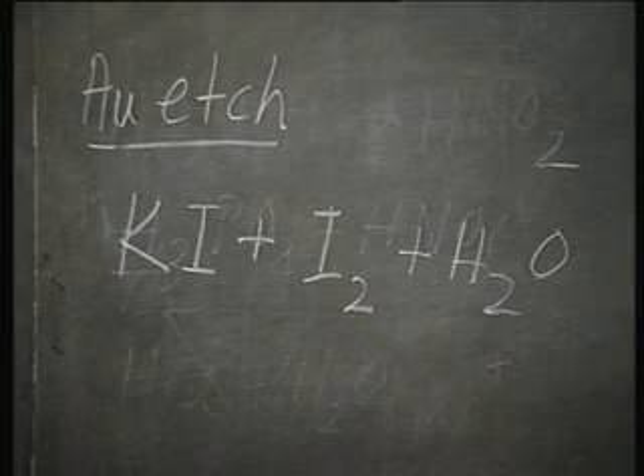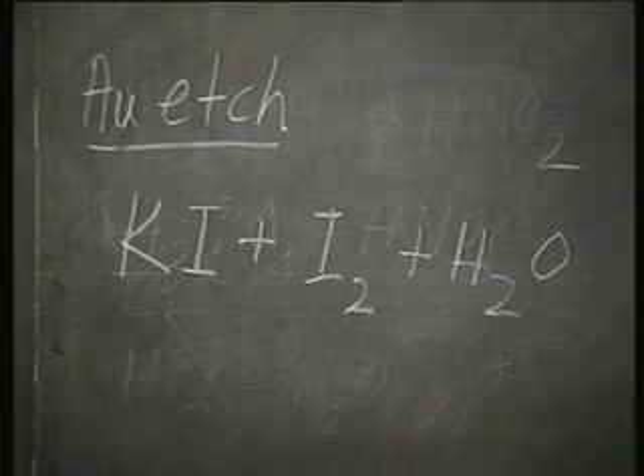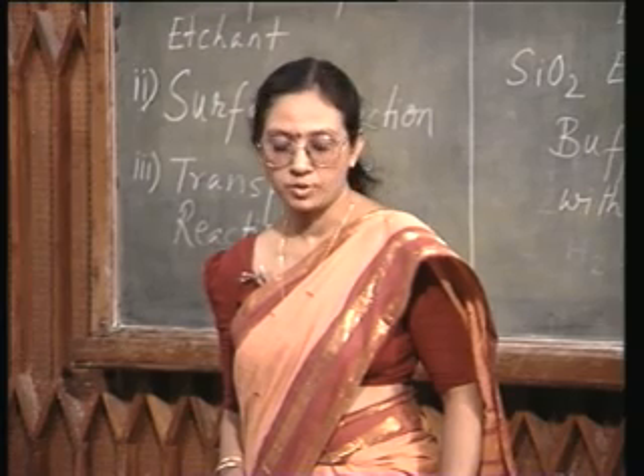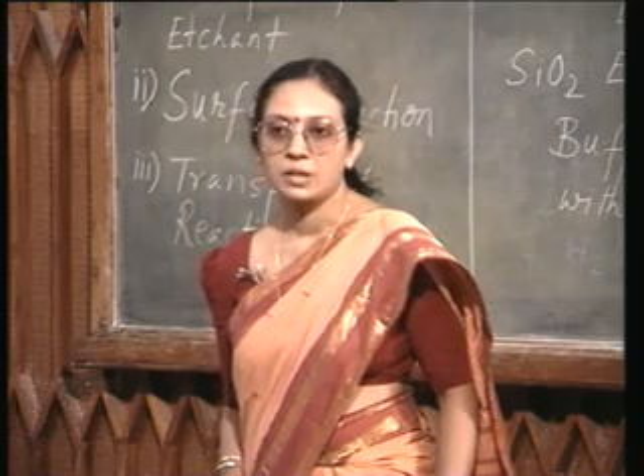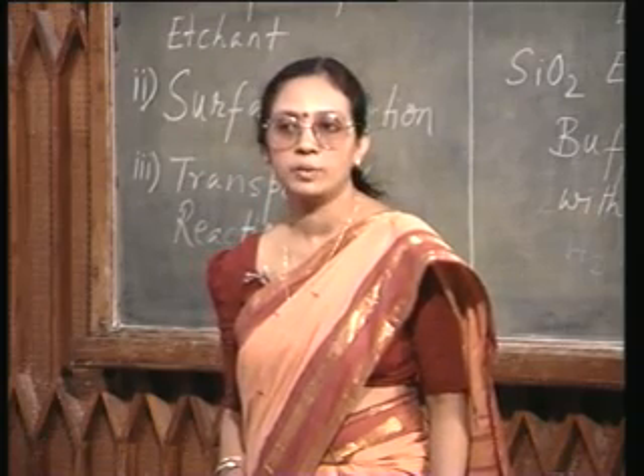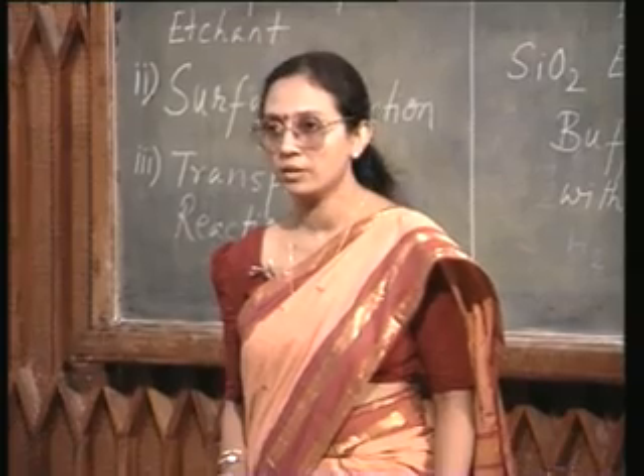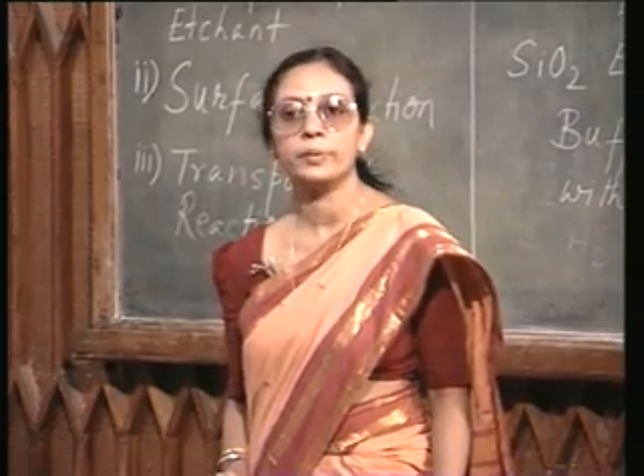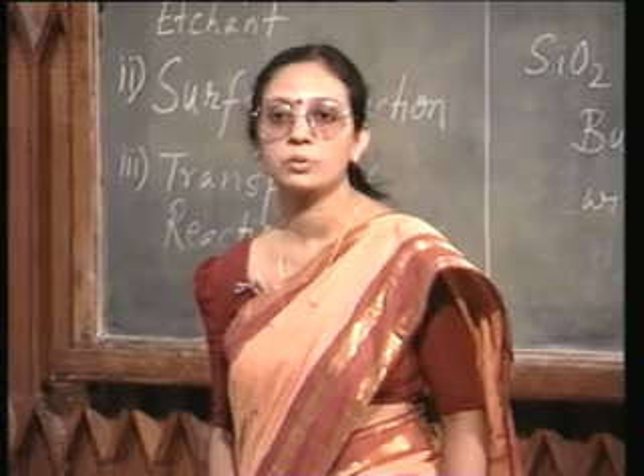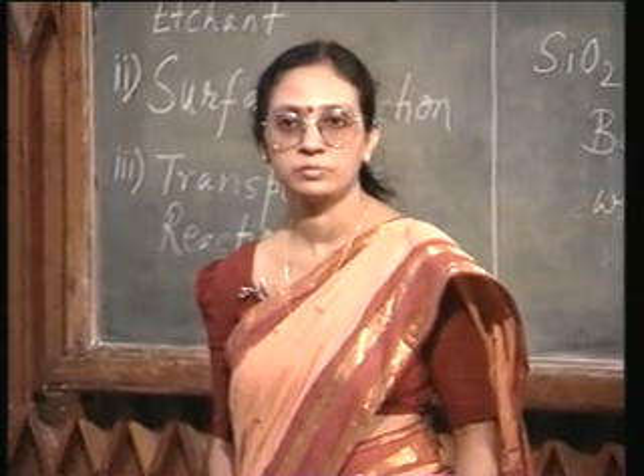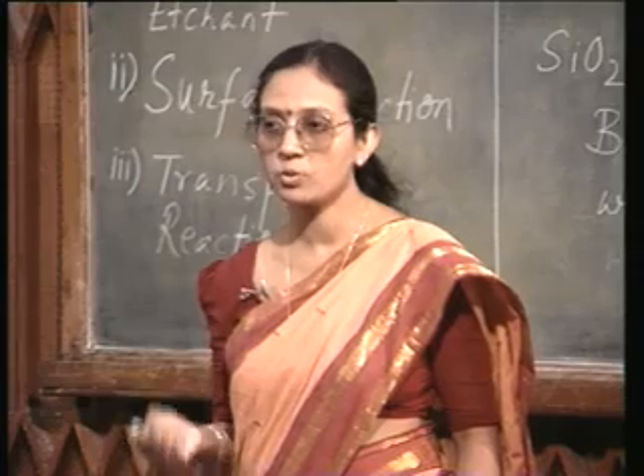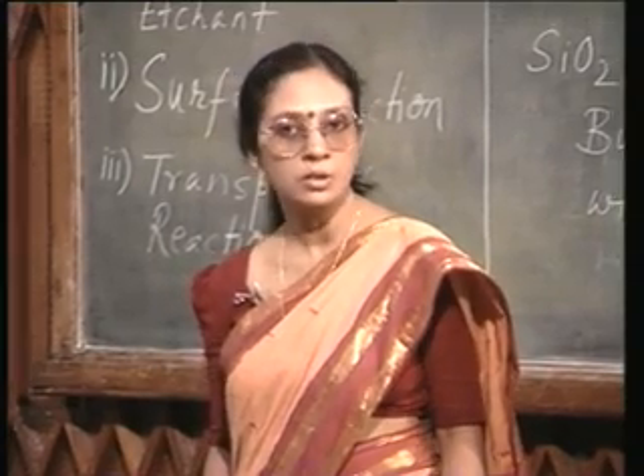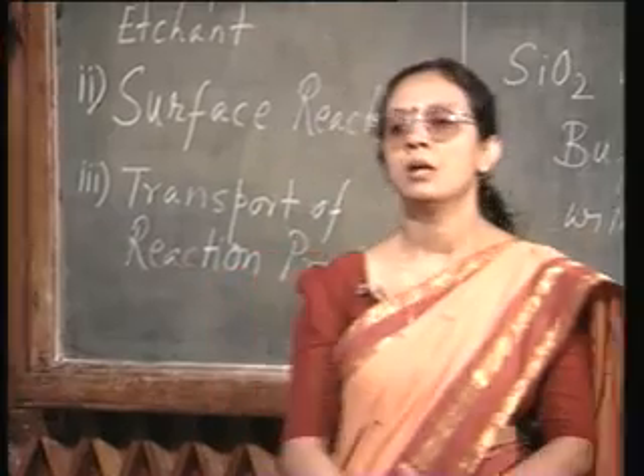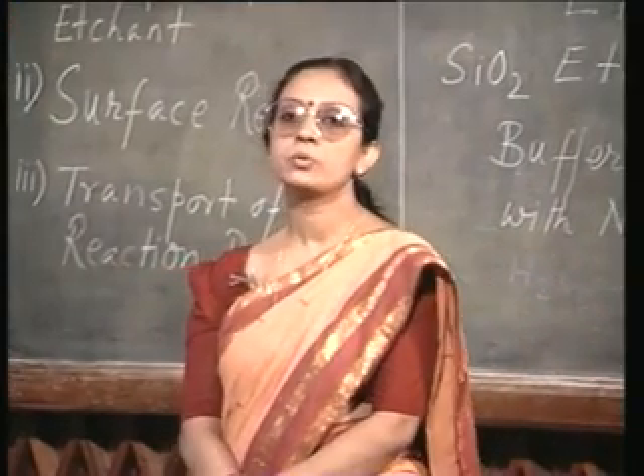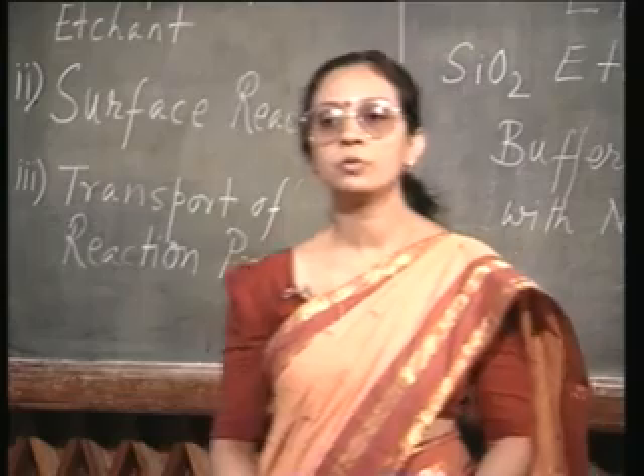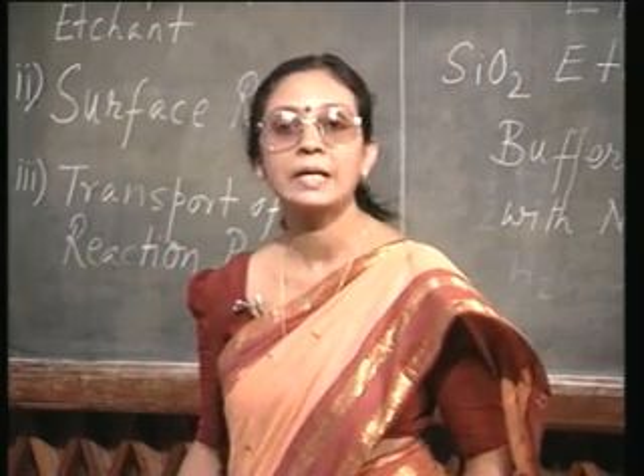Gold is very difficult to etch unless you use this particular solution. But even this solution has a problem. Iodine has a very dark color, so your solution will be totally opaque. You cannot make out whether gold has been removed or not. You have to take it out of the solution, wash it, and only then can you make out whether gold has been removed. That is why we do not normally go for gold etching if we can help it.